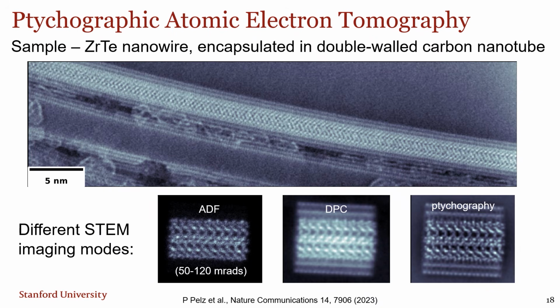So of course, if I show you that technique map here, ADF is that single pixel channel I showed you before. This is unfortunately a high atomic number sensitive technique. So we can see the zirconium and tellurium, but we can't see the two outer walls of the carbon nanotube, right? If we switch to a 4 pixel measurement, DPC here, we are able to get the carbon, but we're blurring out the sample. It's only when we do the full computational pipeline here, this ptychographic method in the lower right, that you can see a very sharp image of all the individual atoms in the nanowire and in the nanotube here.